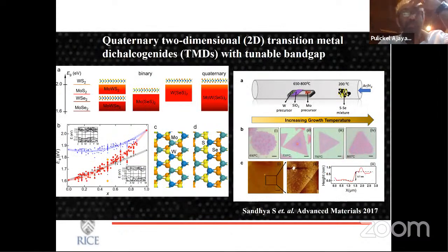But again, before going in and showing some of these potential phase engineering by temperature and other parameters, let me also mention that as you go from binary to quaternary systems, the point is that you can change your band gap in a much more significant way. And again, these are some theoretical analysis that shows that as you go from binary to quaternary, you can expand the range of band gaps by changing the electronic structure.